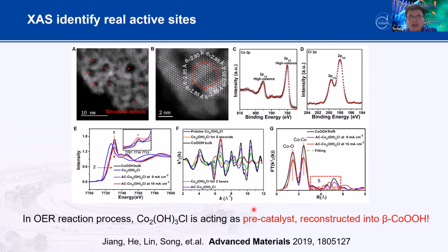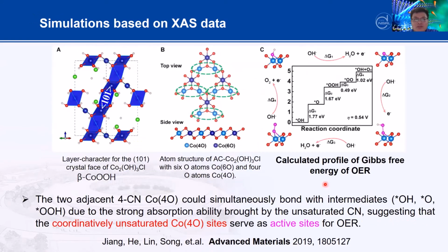So what's the reason? If you combine the XAS analysis, especially of the extended range here, with the simulation, you will see that during the reaction the chloride is etched out and cannot come back. So in this case, the cobalt has only 4 oxygen bonding. This is the light blue color here. They only have the 4 oxygen bonding, so they have unsaturated bonding here. Compared to the active beta phase cobalt oxide hydroxide reference sample, the difference between these two samples is this.